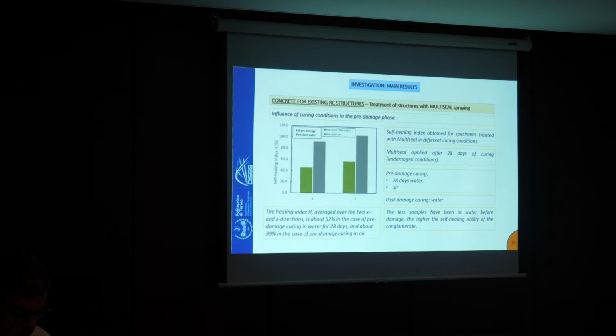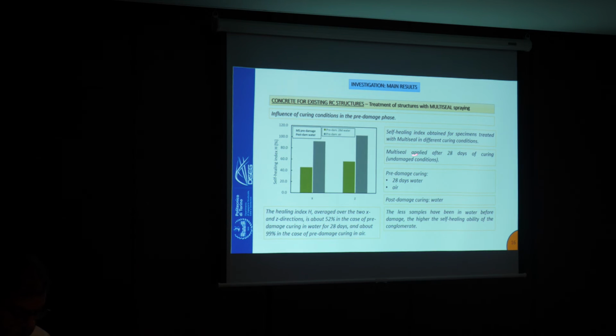While some comparative histograms refer to existing structure, so in this case we treated the concrete samples with multi-seal, and here I show you the influence of the curing condition in the pre-damage phase. Also in this case you can see that if the structure is a new structure realized with the admix plus, or is an existing structure treated with multi-seal, the conclusion is exactly the same. So the less samples have been watered before damage, the higher the self-healing ability of the conglomerate.